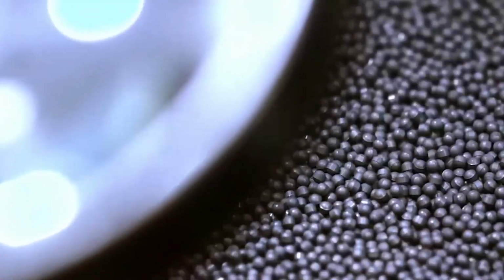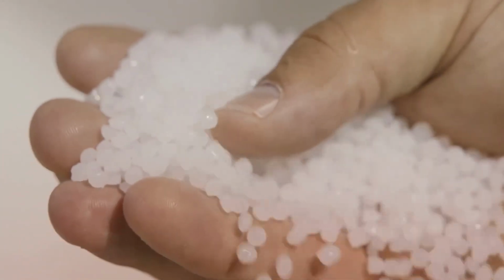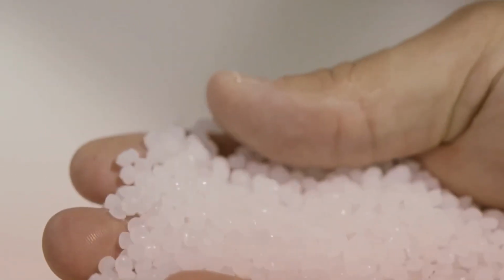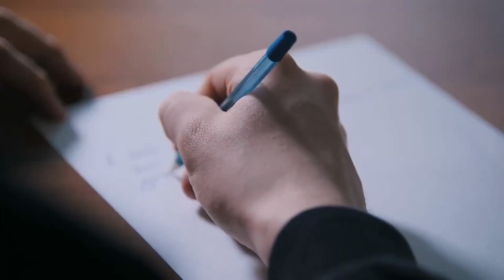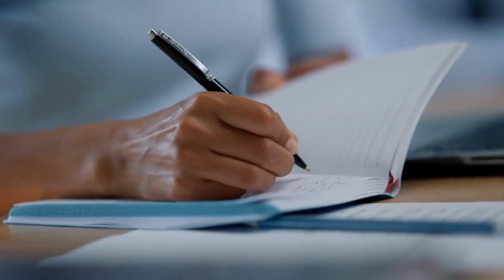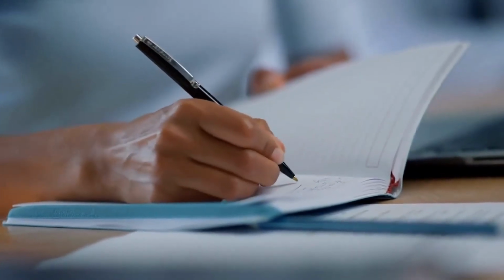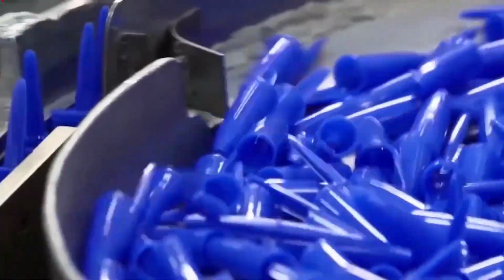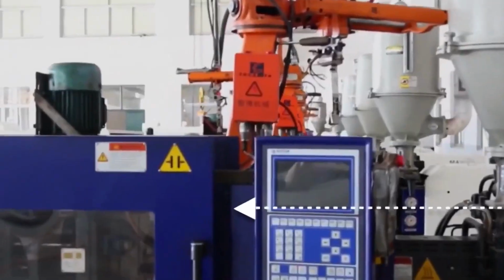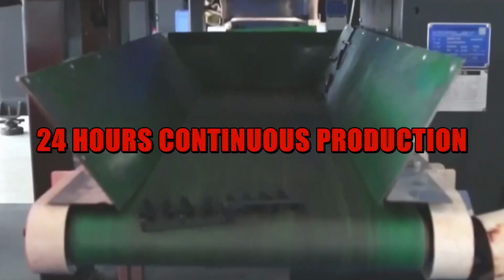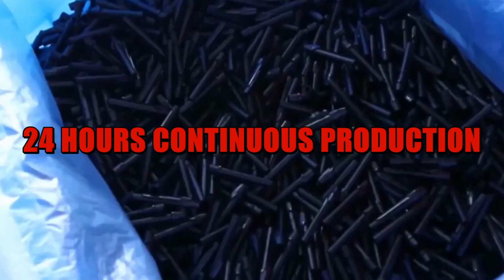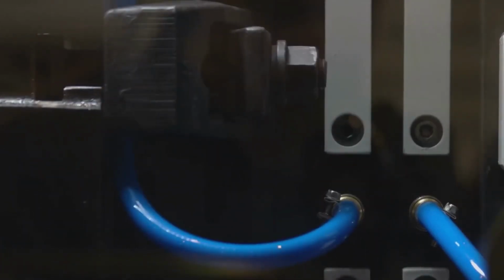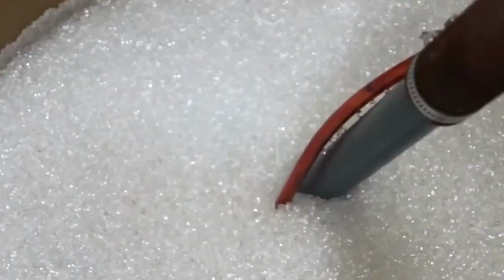Let's see how polypropylene granules, brass sheet, and oil-based ink become 3 billion writing instruments through a production chain precise to 1 micron. The process begins at the hopper. Polypropylene and polystyrene pellets, each roughly 3 mm in diameter, are fed by gravity into injection molding machines running continuously, 24 hours a day. The pellets are heated to between 200 degrees Celsius and 250 degrees Celsius, 392 degrees Fahrenheit to 482 degrees Fahrenheit, until they reach the viscosity of thick syrup.